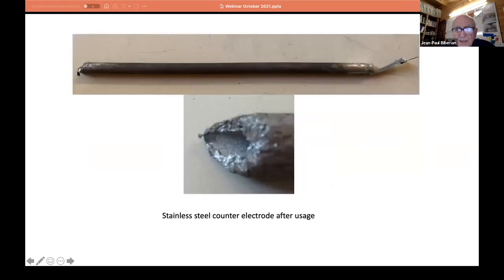You see, surprisingly, this is a stainless steel tube. And look at the end of the tube, it has been completely etched. I'm surprised because the temperature was low. There was no reason that this thing happened. I have no idea what happened there. Something happened. It's very mysterious so far. All these experiments are extremely mysterious.